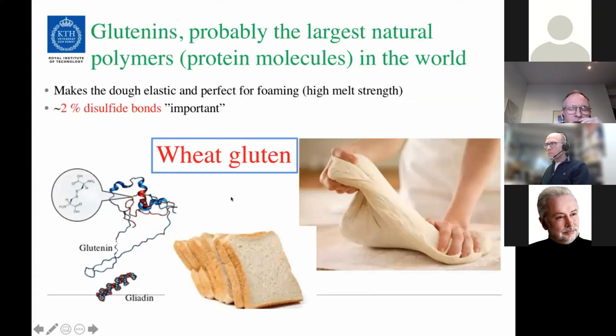I will give most examples now from wheat gluten, which is probably the most cohesive of the normal proteins available. That's because of its very large molecules. The glutenins, which are part of gluten, are probably the largest molecules in nature. And when you bake, you're actually polymerizing the material even further. You do a polymerization and a cross-linking event when you're baking. That's why the dough becomes stiffer and stiffer when you knead it, and also when you heat treat it.